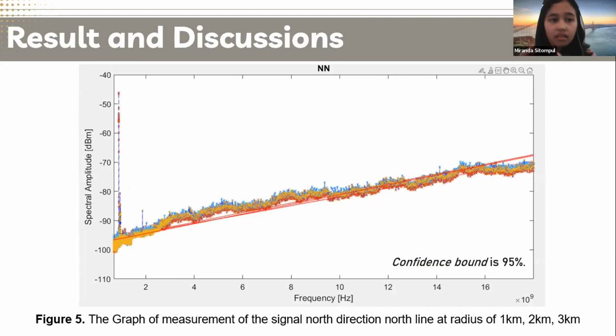Okay, this is the result from my research. We can see the figure 5, the graph of measurement of signal north direction, north line at radius of 1 kilometer until 3 kilometers. From the graph, we can see that spectral amplitude is in the range of minus 45 decibels to minus 100 decibels. And from the measurement of 3 data with distance variation, we can see that the data obtained are similar, and they show that there's no material around the measurement point that interferes with the measurement at that distance. And we can see the confidence bound is 95%.